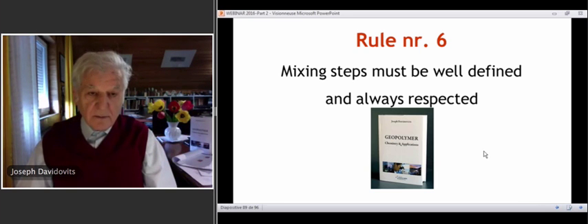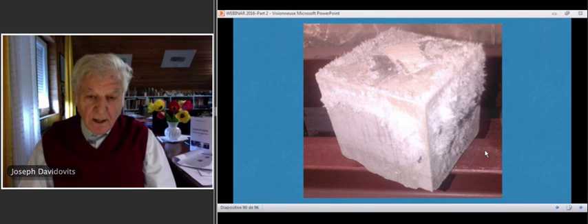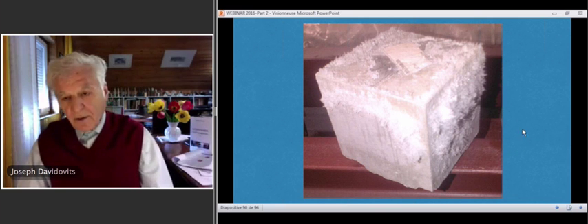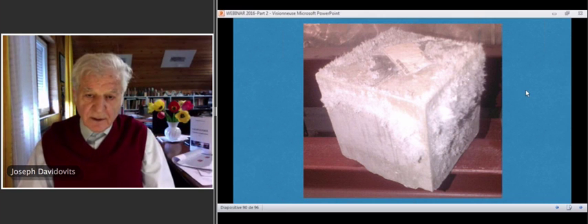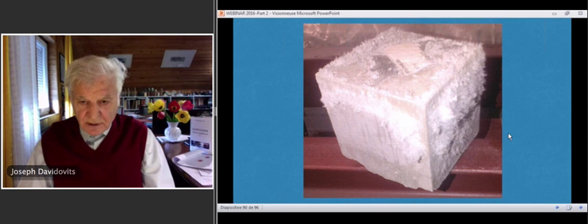Rule number 6. Mixing steps must be well defined and always respected. I received a lot of emails from people who are discouraged by the fact that when they mold what they have done and leave it in the air, after some days it is covered with whitish blooming and so forth, and they ask, what is it, why? Well, this is a result of alkali activation, an alkali system added to a system that you don't control, which yields this drawback, a very bad system.